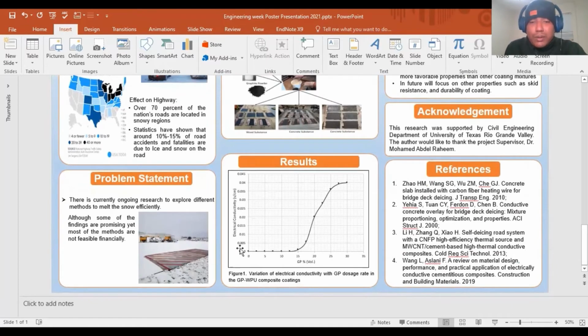To determine the optimum amount of graphite dose in the polymer content, along with achieving the desired conductivity of the composite, we used a tool called the percolation threshold, which is an excellent method to explain the electrical behavior of the composite. The polymer content in the matrix works as an insulator. To reach higher conductivity of the composite, conductive filler should be introduced in the composite after percolation. Therefore, to create the continuous formation of conductive paths in the whole matrix, the volume fraction of conductive filler should be greater than or equal to the percolation threshold.